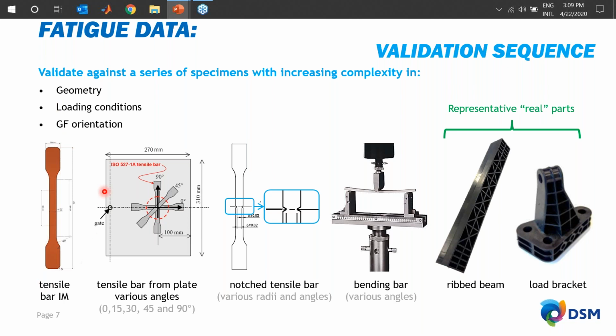So you can imagine that we start with a typical standard injection molded tensile bar, so highly oriented fibers. We also move to samples that we mill from a plaque. So from an injection molded plaque, we take tensile bars from different angles. And instead of just using the minimal of 3 that is usually used for calibration, we also studied other angles, let's say 15 and 30 degrees, to see how well we can predict the influence of anisotropy.